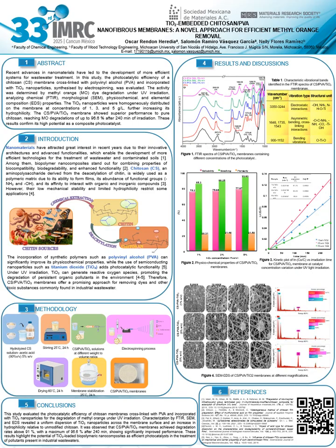These results highlight the synergistic effect of adsorption by chitosan and PVA and the strong oxidative capacity of titanium dioxide under UV. The degradation data fitted well to a pseudo-first-order kinetic model, as described by the Langmuir-Hinshelwood equation. The rate constants k increased significantly with titanium dioxide content. The 5% titanium dioxide membrane exhibited a k value approximately 2.5 times higher than the 1% membrane, evidencing the critical role of titanium dioxide loading in accelerating the generation of reactive oxygen species, ROS.